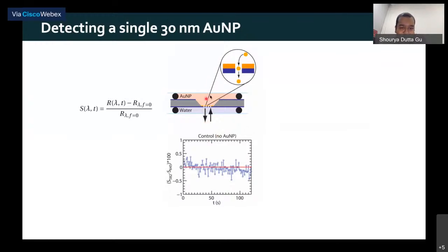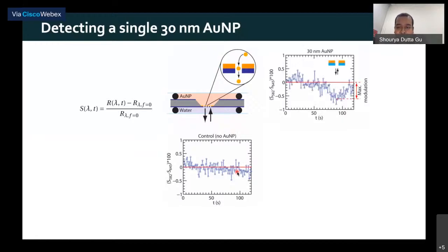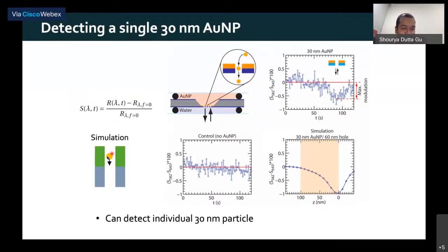Now, if both of the chambers are filled with water, and you measure as a function of time, you will see no signature or no signal change. It will be practically zero. However, if you put these nanoparticles in the top chamber, you will see signals like this. Till some point, the signal will be zero. After some point, you will see some modulation. This modulation comes from these nanoparticles. You can simulate it by putting these nanoparticles at different positions in the channel, and you'll get a similar response as compared to the experimental result that we have.